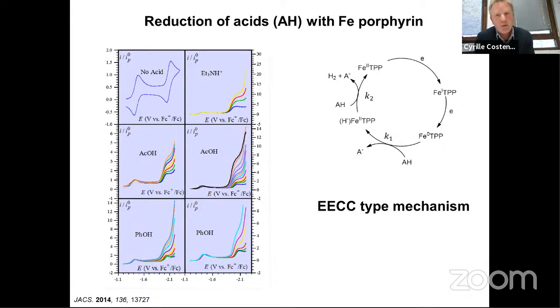Okay, so now let's continue on iron porphyrin, but with a different mechanism, with a different example, which is the production of hydrogen. So you can produce hydrogen by using iron porphyrins again, because once you generate iron 0, you can have a reaction here with an acid molecule to make a hydride, which can react with a second acid molecule to make hydrogen and regenerate the catalyst. So you have an EECC type mechanism.